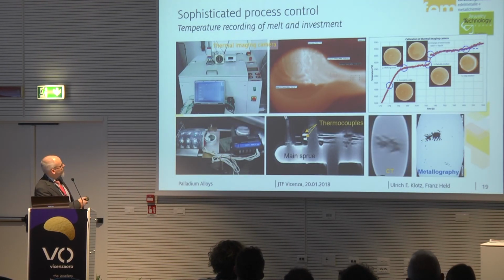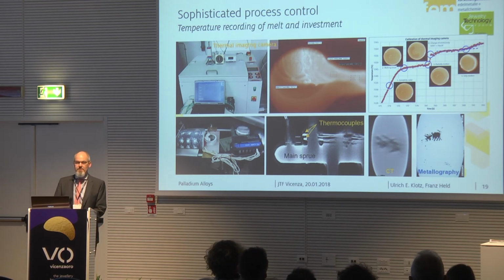Casting is done in standard flasks. Here you see the situation after casting. We used thermocouples that we mounted inside the trees. So here's an example. You see the thermocouple inside the main sprue, and this allows us to measure the heat up of the investment, which can decompose and react.